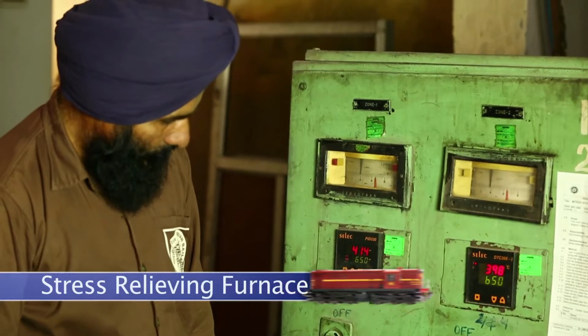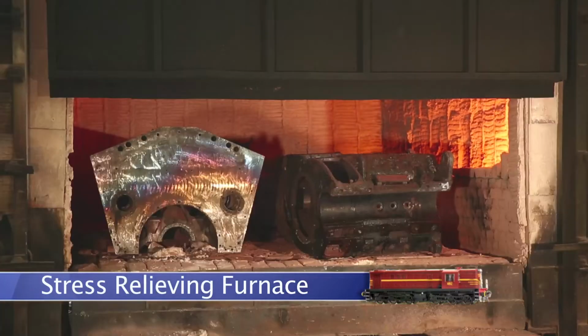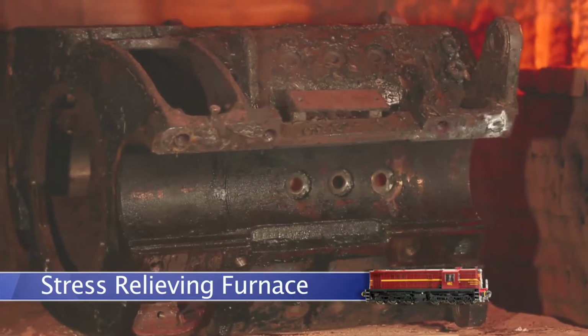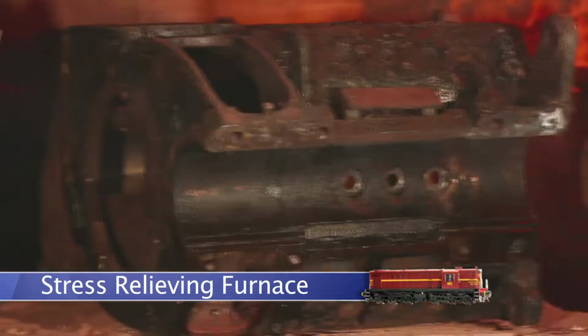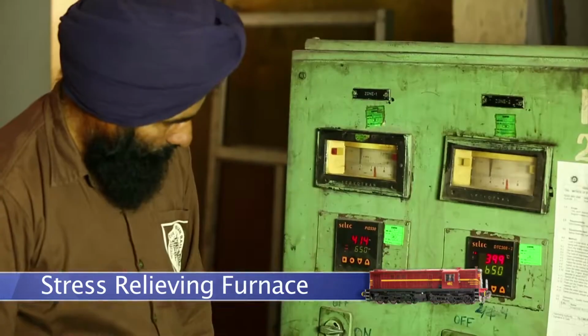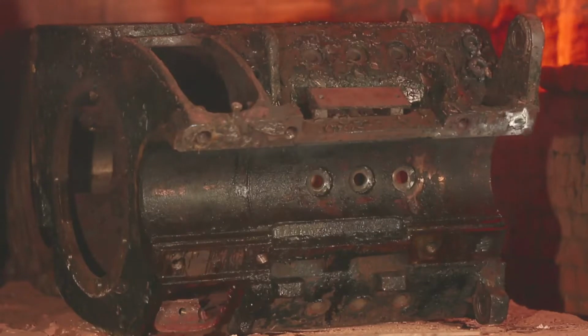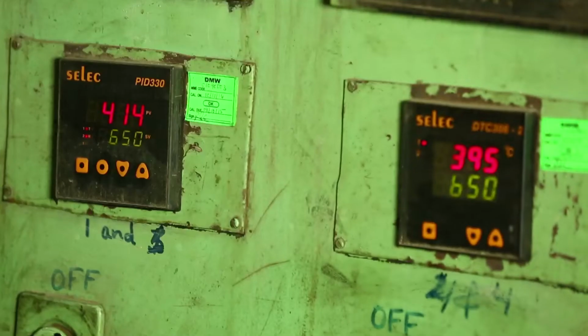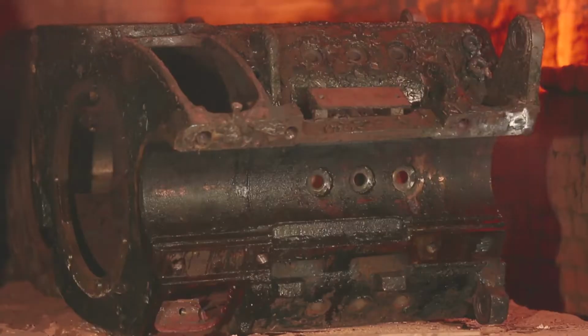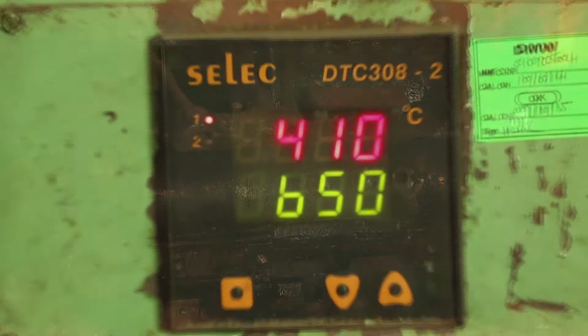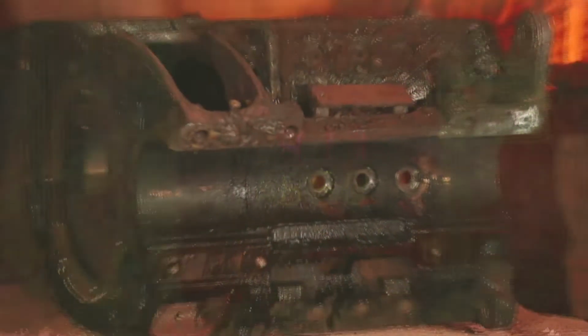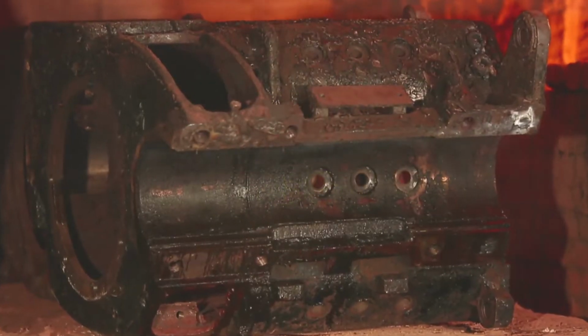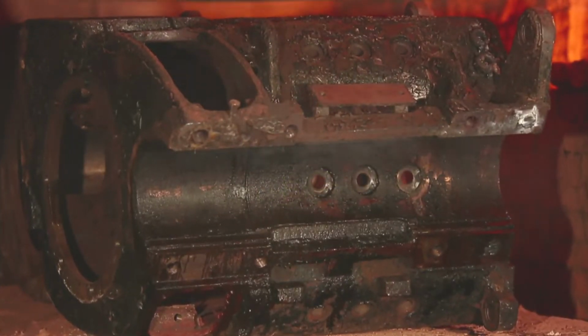The stress-relieving furnace is used to relieve internal stresses of magnet frames and engine blocks which develop during welding. It also increases machinability of components. The components are heated at the rate of 70 to 80 degrees centigrade per hour up to 650 degrees centigrade and held at that temperature for soaking period of 4 hours.